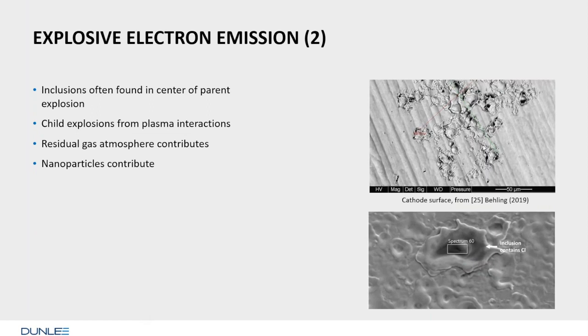This is a picture. You can find it all over in every X-ray tube you open. If you look into a scanning electron microscope, and I did this last year, this is exposures from that, you see craters on the surface. They're pretty small, 50 micrometers, this bar here. If you look into the craters, you see different sizes of craters. One is large, the other ones are smaller, and in the middle of the large one, we see that there was an inclusion which contains chloride.